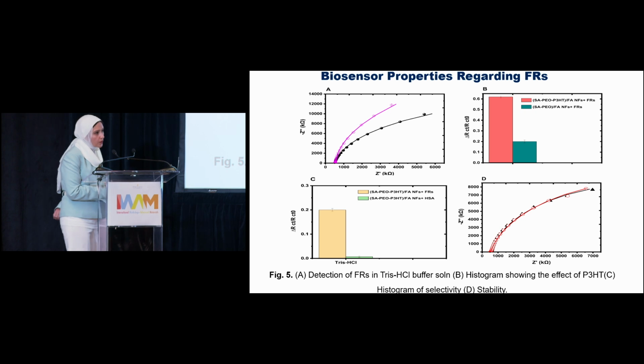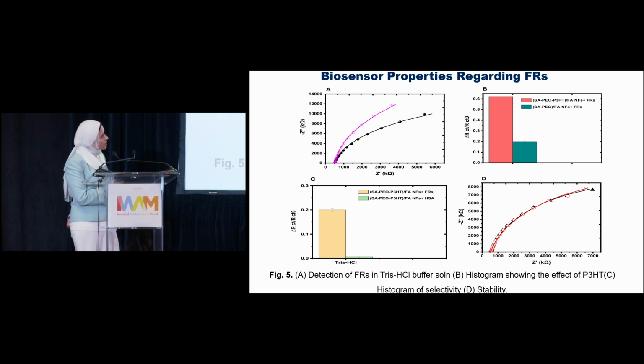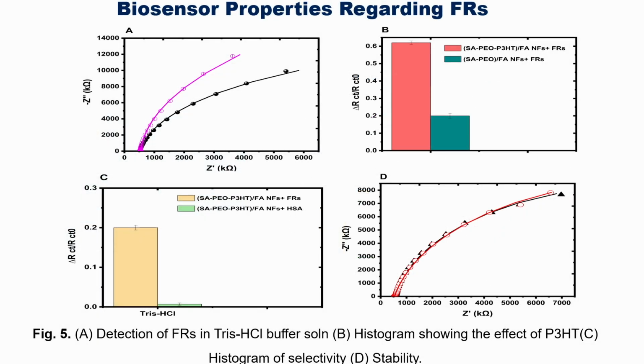Here we investigate the detection behavior of our biosensor for folate receptor in Tris-HCl buffer. As we see, there is an increase in the diameter of the semicircle of the Nyquist plot. This increase in the diameter rose gradually with increasing concentration of folate receptors, and this confirmed the sensitivity of detection of folate receptor even in the buffer solution. It was around 10 nanomolar, the concentration of our protein.